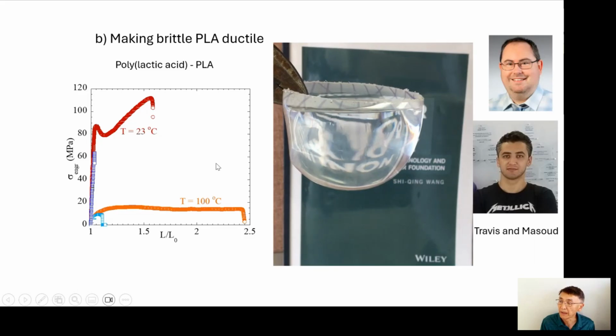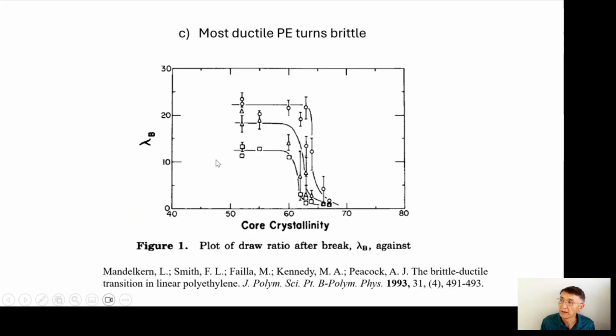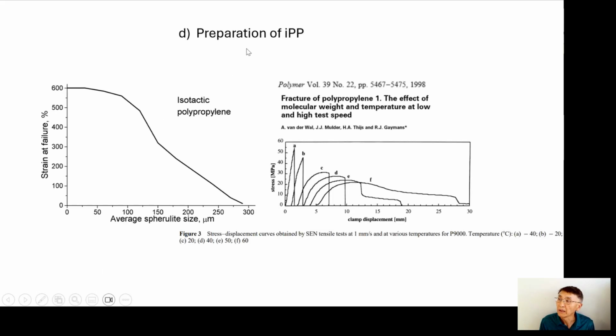So this is something that we have previously established. It is also known that the most ductile polymer, such as polyethylene, can be brittle if you have too much crystallization. Why? Well, that's something we think we understood very well now. And PP, polypropylene, is growing in market share, but it is not one of the most fast crystallizing material. So depending on how you control the crystallization, you can get huge morphology differences, and that affects ductility.